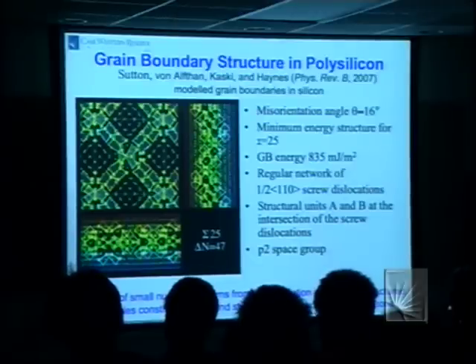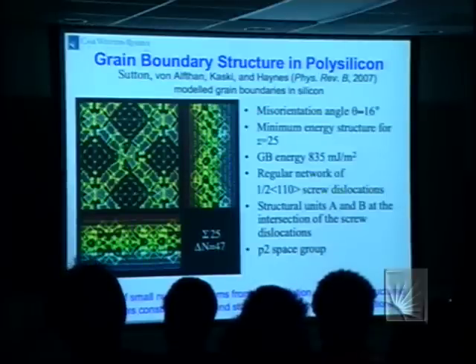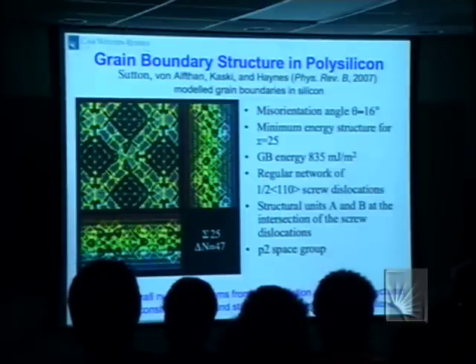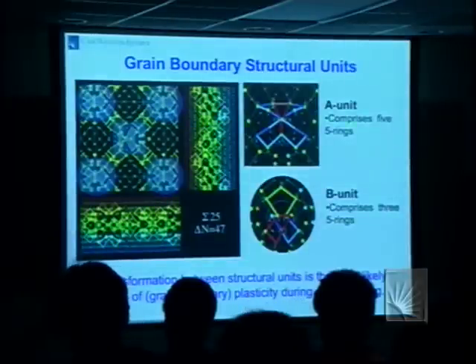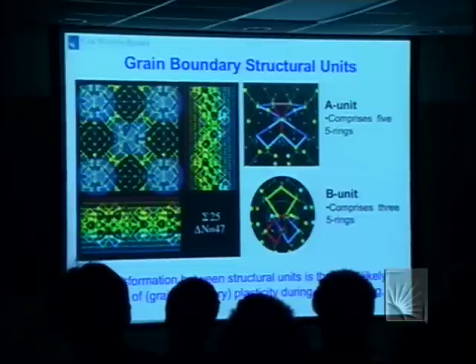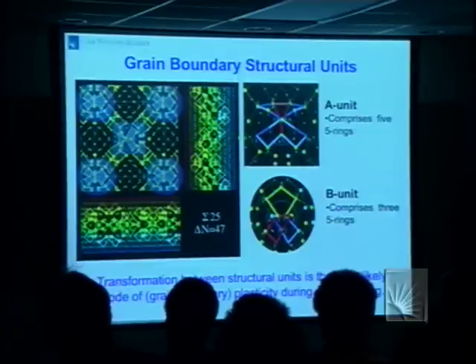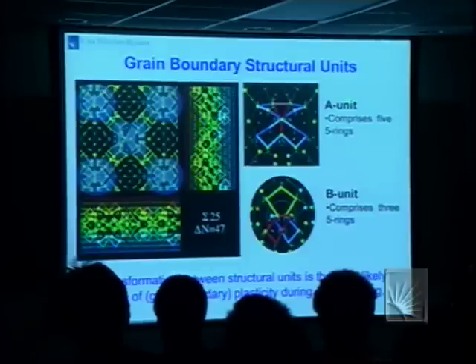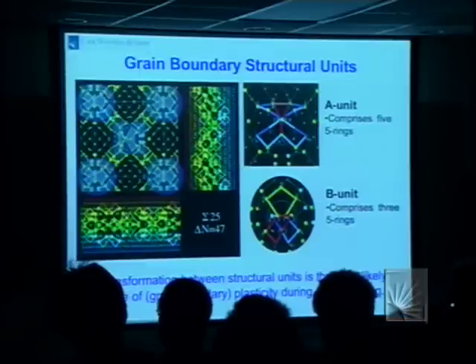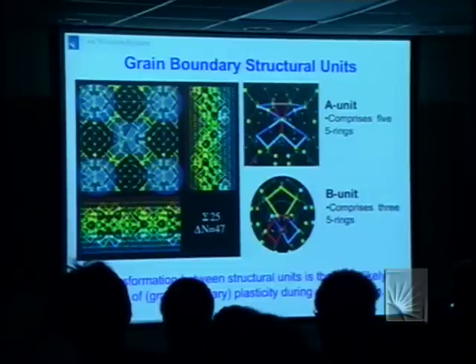grain boundaries of any misorientation, over the whole range of misorientations, the boundaries are not just an amorphous melange, but they're structured. And in the structures, there are these A units and B units, which refer to specific arrangements of silicon atoms in the grain boundaries. The proportions of A to B change with misorientation. And it's entirely possible for very small motions of atoms in the grain boundaries to cause an A unit to irreversibly transform into a B unit.